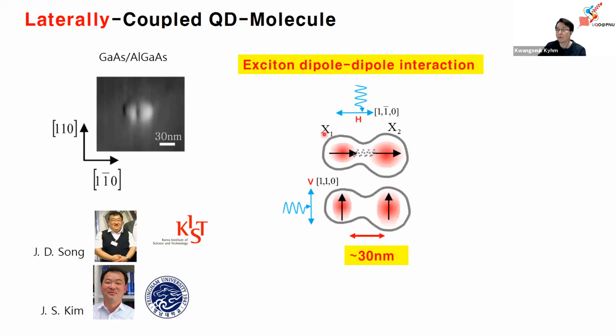However, we have to consider dipole-dipole interaction. In the case of dipole-dipole interaction, the alignment of the two exciton dipoles is very important. For example, if the two dipoles are aligned along the coupling direction by using linearly polarized, we call it H-polarized, light parallel to the coupled direction, the interaction becomes maximized. On the other hand, if the dipoles are perpendicular to the coupled direction by using V-polarized linear excitation, then the interaction decreases a little bit. So our idea is very simple: using linearly polarized light, we want to control the alignment of the dipoles and control the interaction between two quantum dots.